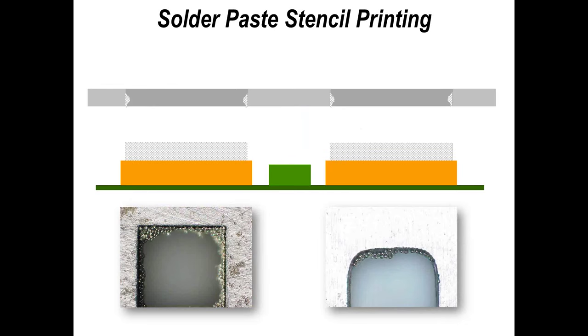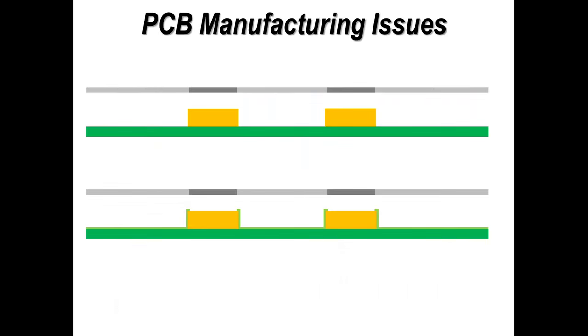Now, in this example, with the photographs at the bottom of the slides, I just show you solder paste deposit still left in the apertures. Now, generally speaking, with design today, most companies tend to round off apertures. They don't have to have square apertures or truly square. So there tends to be slight rounding off. The reason being the solder paste or conductive adhesive separates more cleanly and, of course, gets closer to 100% deposit from the intended design of the stencil aperture.